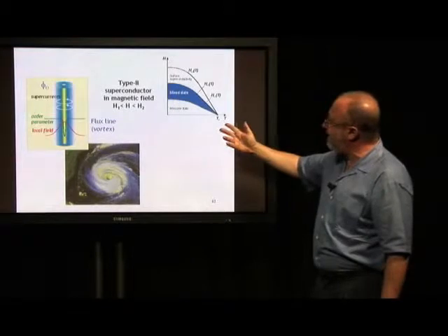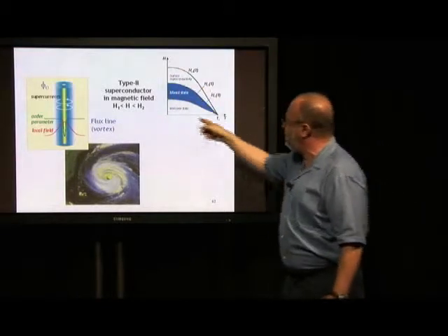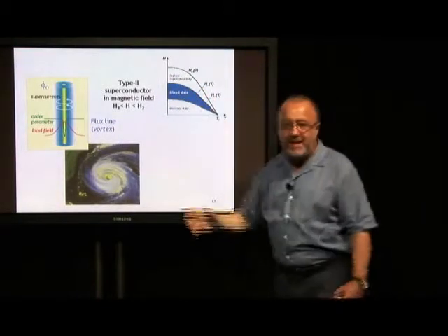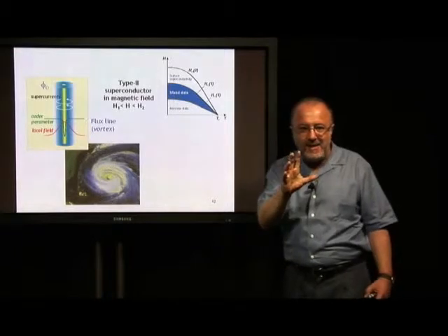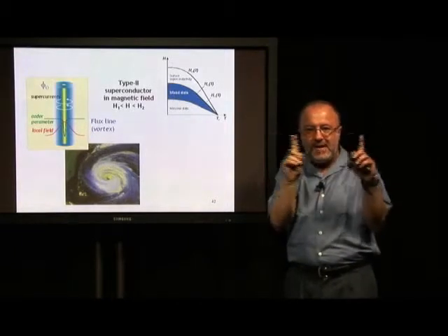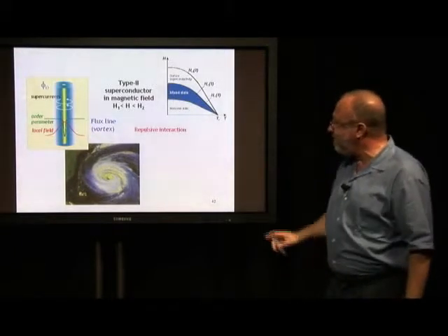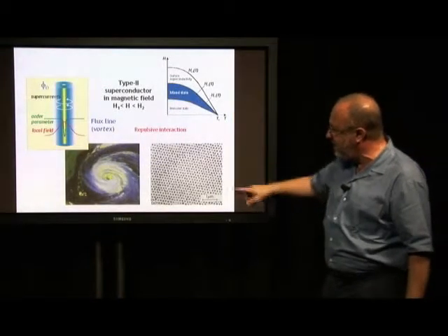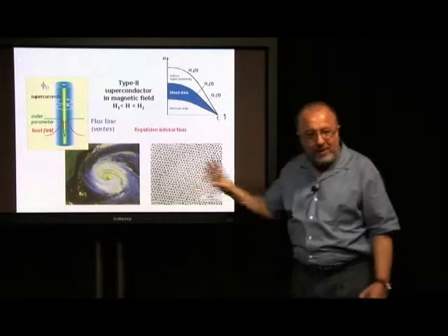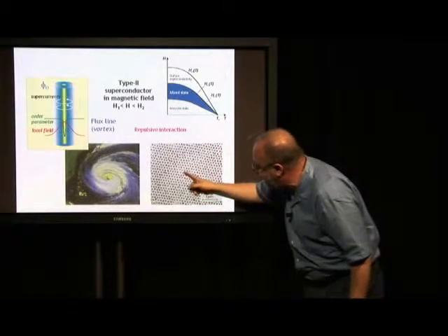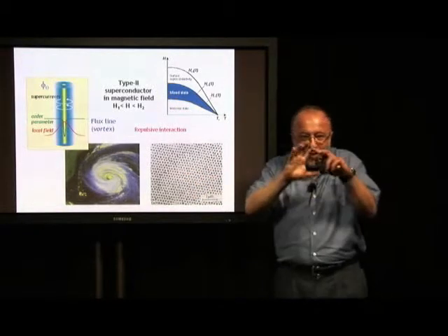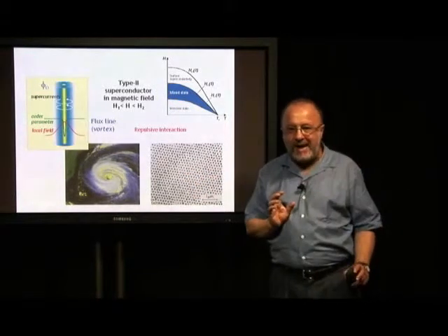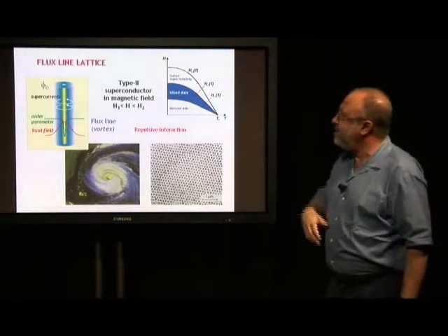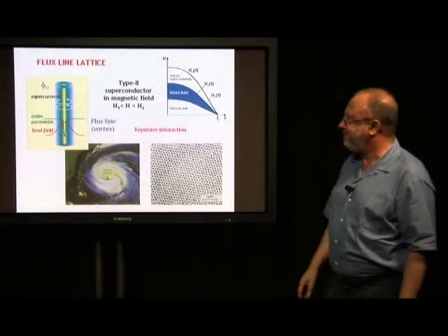So that's how the phase diagram looks. There's magnetic field versus temperature. In this region, there is the so-called mixed state. And in this mixed state, these vortices interact strongly with each other. As these vortices interact, because of the repulsive interaction, they form a lattice. If you look very closely here, you will see that there is a hexagonal lattice. The thing orders itself into little triangles. And this is what is called a flux line lattice.